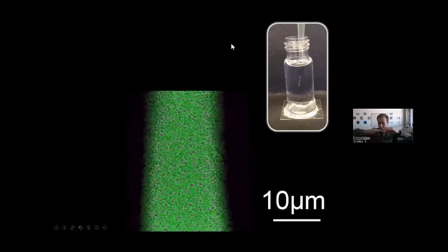We take a so-called Z-stack, where we scan like a tomograph through the material, and then we have fluorescent labels, one that labels the water in magenta, the other that labels the particles in green. And you can see this scan here shows that the bicontinuous fluidic network within this fiber is extending from the surface deep into the material.